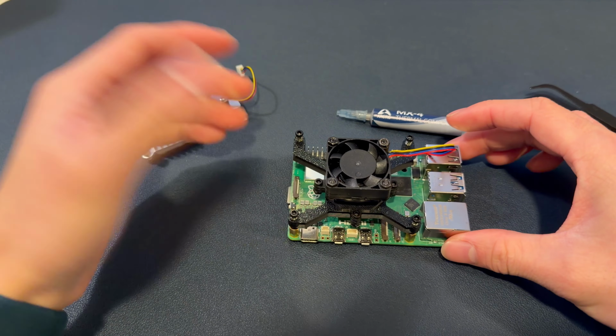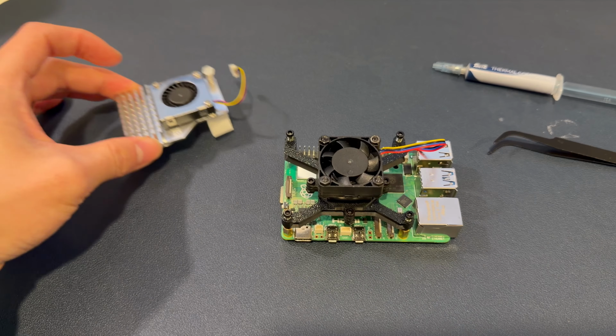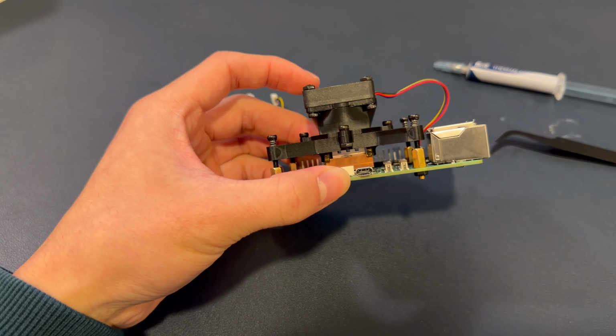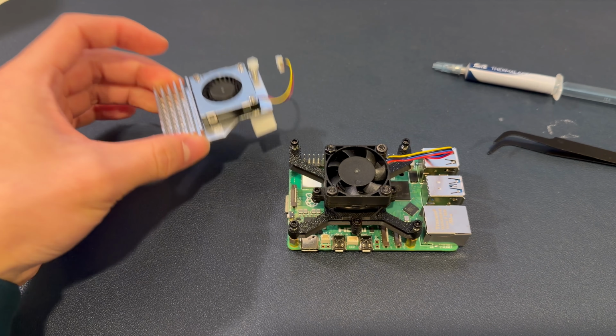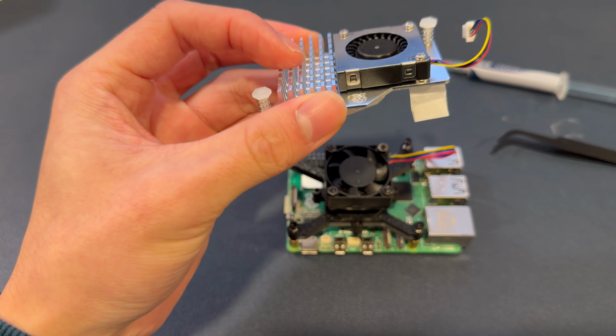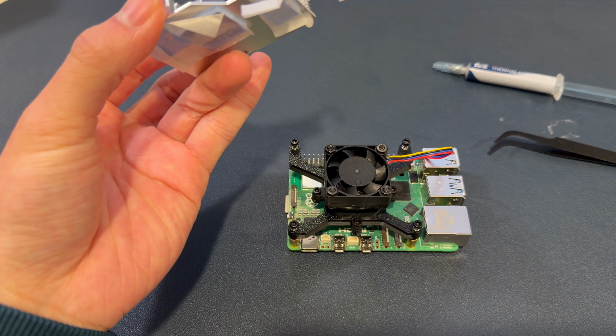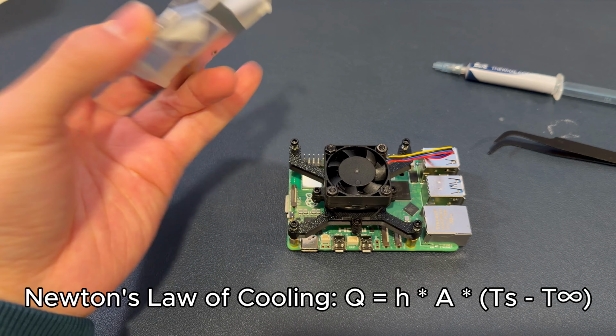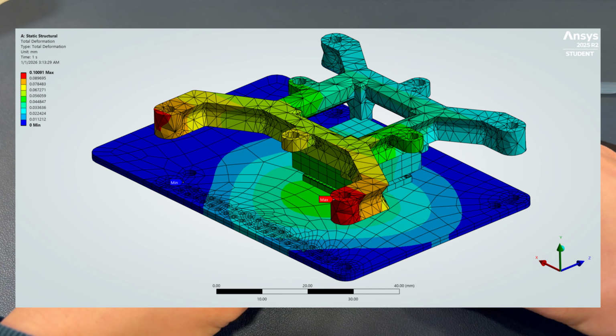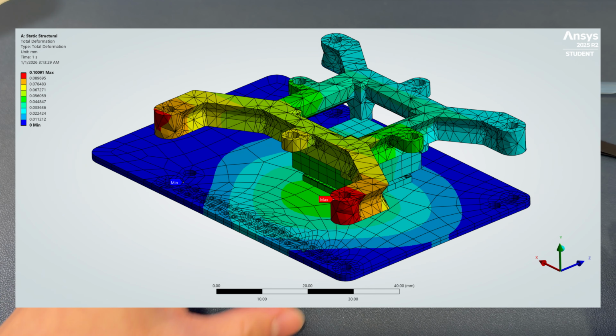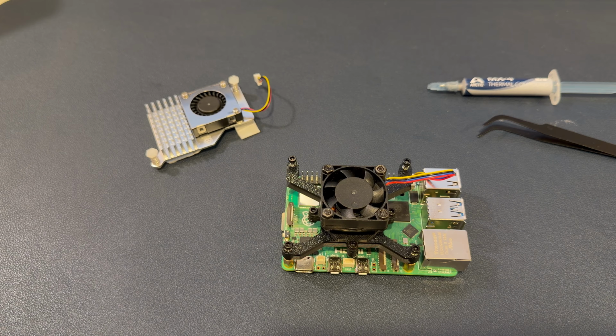And this highlights a classic trade-off. While the copper has higher thermal conductivity, the active cooler wins because of its 54 fins, which is crucial for heat dissipation through surface area. Using ANSYS, I verified the structural integrity of the PETG bracket and ensured that the deflection of the mounting bracket and bending of the PCB didn't exceed far past 0.1 millimeters.